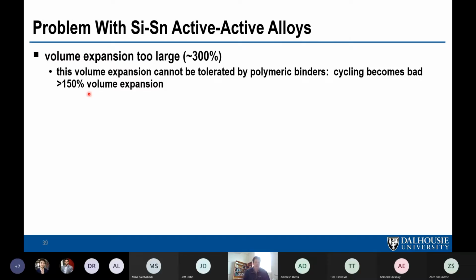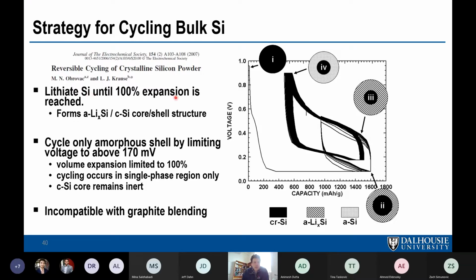And at 100% volume expansion, a silicon alloy will have about double the volumetric capacity of graphite, which is about the minimum you want. That corresponds to a 15% improvement in cell energy density, and anything less than that is not really worth it. You can get 100% volume expansion even with pure silicon if you take advantage of its unique electrochemistry.